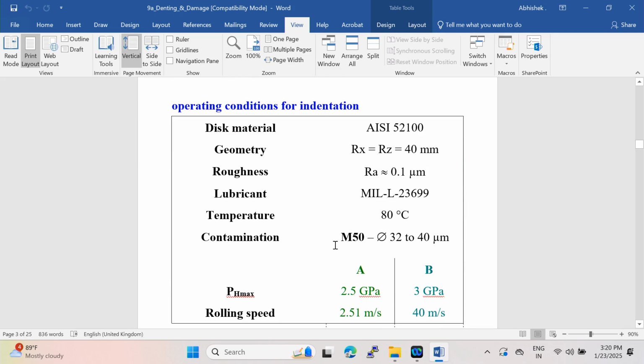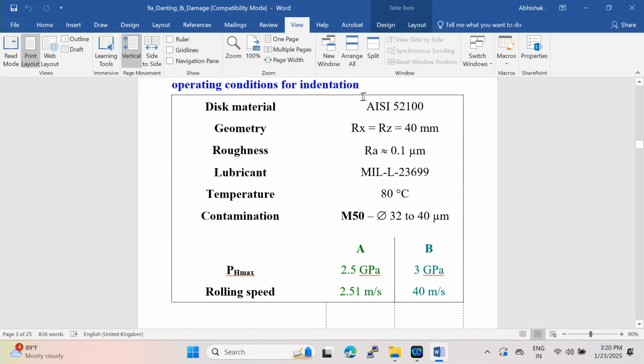Then typically this is what we use as material. It's a 52100 steel disc of radius 40 millimeters with a high quality roughness, 0.1 micrometers. The lubricant is an aerospace lubricant, 5 centistokes at 100 degrees C, which is used for most engine bearings, turbine engines. Temperature is 80 degrees. Particles are made of M50, and here the size is from 32 to 40 micrometers. Okay, it's easier to manipulate.